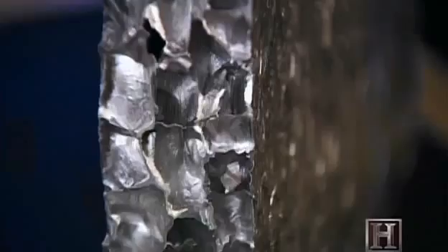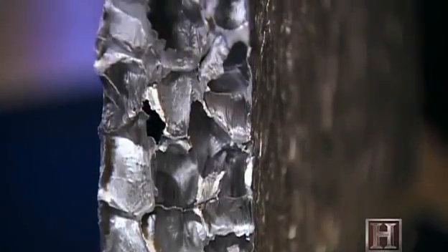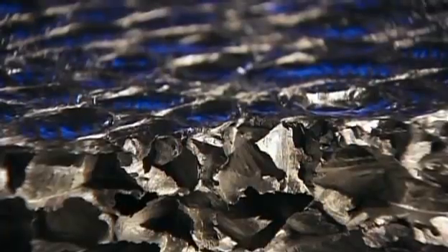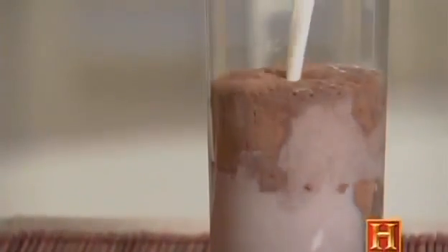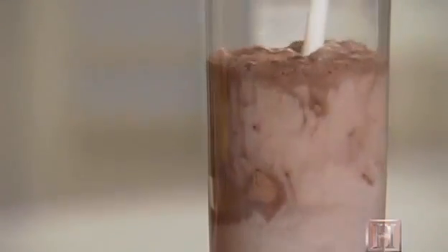Aluminum foam's key ingredient is nothing more than air. But the real trick to making it isn't injecting air bubbles into the aluminum. It's keeping the bubbles intact once they're inside. Our material is molten aluminum with ceramic particles in it. Those particles stabilize the bubbles, in other words, stop them from popping. And a good example of this is if you've ever tried to use dried cocoa powder and mix it into milk. And as you're doing that, you see this froth forming on the surface with the dried cocoa on the bubbles. The bubbles are stable.